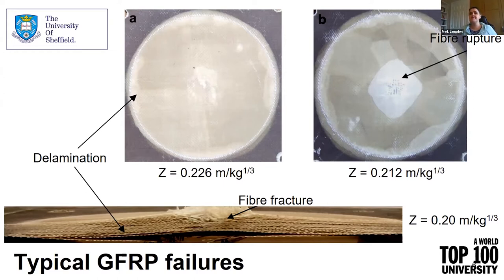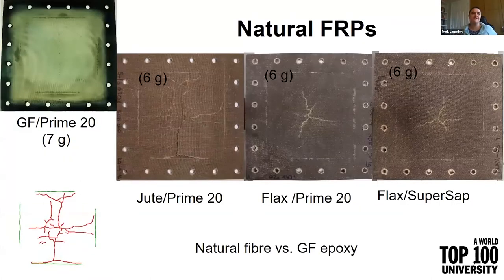This is a very brittle type response to very extreme high rate loading. You see matrix cracking, delamination, fiber fracture, fiber matrix debonding, through thickness rupture and mixed mode failures. Extremely difficult to model computationally if you want to try and model this at some sort of scale of modeling that allows you to do engineering design. And we've already heard that this morning from some of the other speakers when looking at impact applications.